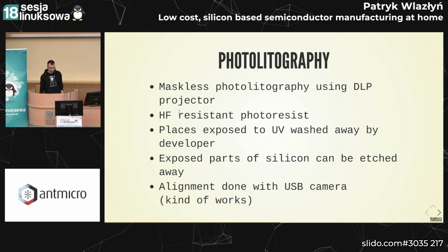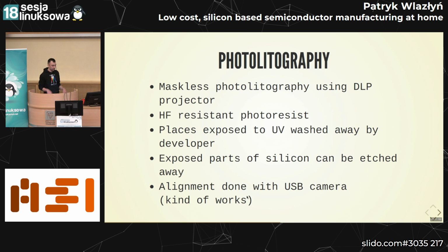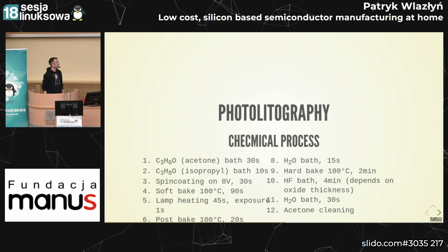Using the DLP projector, the photoresist is HF resistant, so we can use the chemical process I described on the previous slides for etching the silicon dioxide without attacking the photoresist, so it acts as an insulating layer. Places exposed to UV are washed away by the developer, and exposed parts of the silicon dioxide can be etched away. And when we have this photolithography step, you have to align properly, so you know where you're going to be shining on the photoresist. We have a USB camera setup that I will show you shortly.